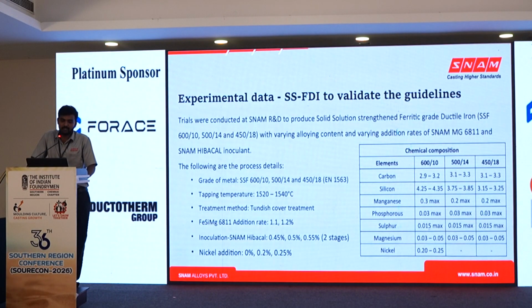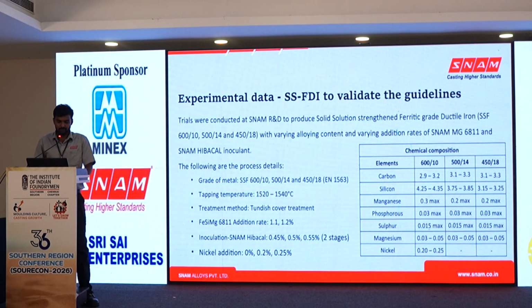FeSiMg we have used common grade 6811 magnesium grade at the addition rate of 1.1 to 1.2. Inoculation is we have used barium based inoculant 0.45 to 0.55 in two different stages, one in treatment ladle and another is transfer ladle. We also added nickel based on the requirement from 0.2 to 0.25%.